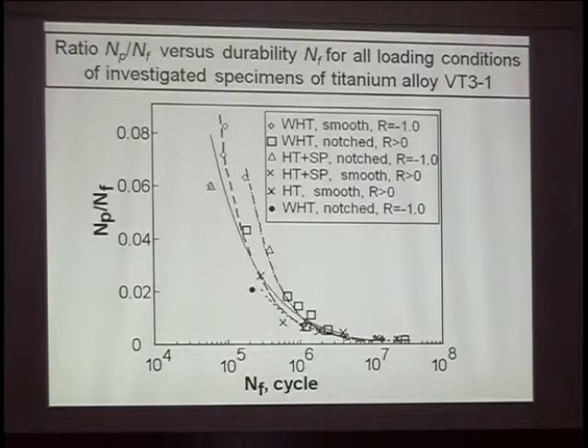In that case, first of all, this manner of cracking always exists because of the mesotunneling effect. Cracking exists not along the whole crack front, only at the tunnels, and then there is an interaction effect between two or maybe three mesotunnels. This interaction effect can delay material cracking. That's why we can see small cracking, but then it takes time to crack the neck between two mesotunnels and maybe a third, a fourth. Then the whole crack front will be organized. So it will be a really long time to realize this very complicated way. Okay. Thank you very much. Sorry.